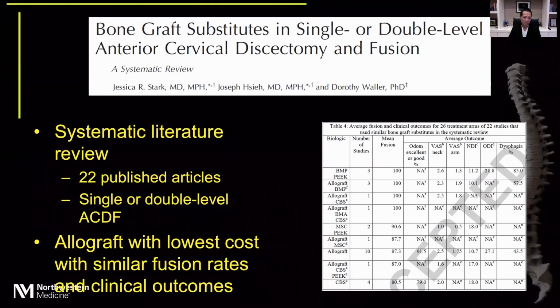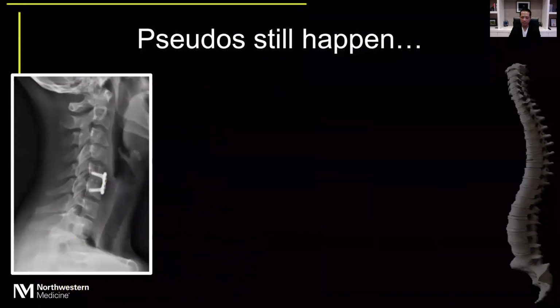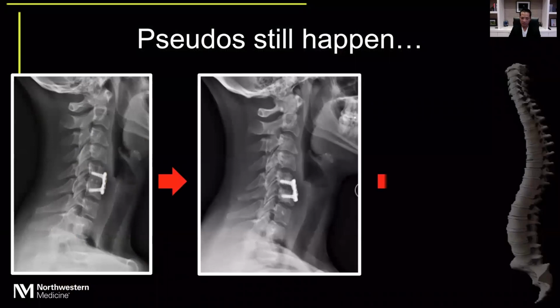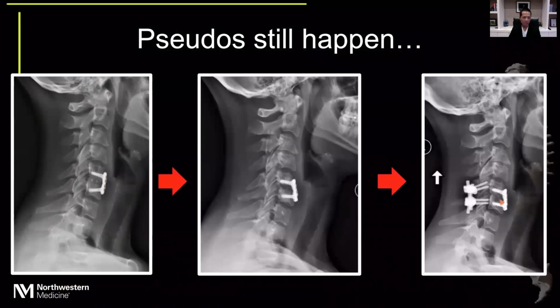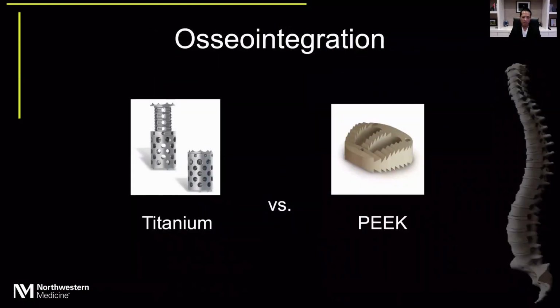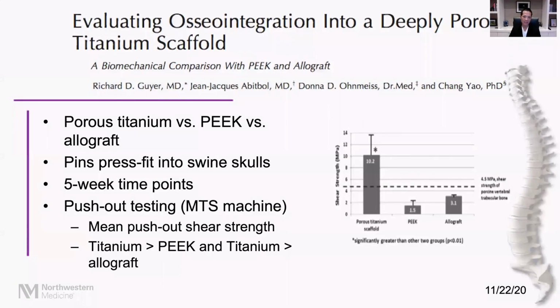And then systematic literature review has shown that allograft has the lowest cost with similar fusion rates and clinical outcomes when compared to PEEK and other types of materials. But we know that with the use of allografts, pseudoarthroses still happen. And the large reason is because these grafts can resorb, and if they resorb, then we lose stability at that level.